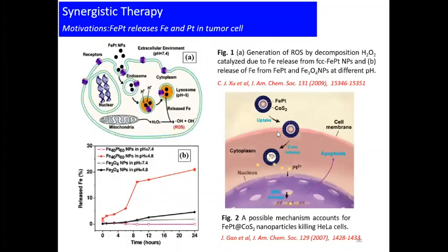Since it's about biomedical application, I'll touch a little on the biomedical applications. Iron platinum is one of the good materials which people have predicted releases iron and platinum. Iron, when it goes into the cells, decomposes the hydrogen peroxide in the mitochondria and provides reactive oxygen species, and this oxidizes the material, leading finally to the death of the cancer cells. These are some of the results taken from this paper, and the iron platinum releases more iron than the iron oxides. In some papers, it has been found that the platinum specifically binds to the DNA of the cancer cells and changes the sequence.